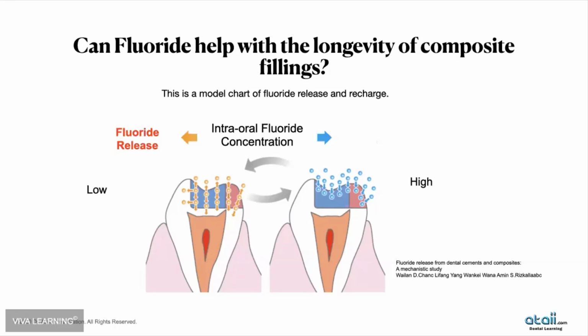Why I say that is because a lot of times composite materials have fluoride in them, but after the first half an hour, studies show that a lot of composite materials release the fluoride and they don't recharge. What that means is that the fluoride is within the composite resin, the acidity hits it, and at that point the fluoride is gone, dissipated, and it doesn't get recharged. The actual composite resin does not have the ability to release additional fluoride.